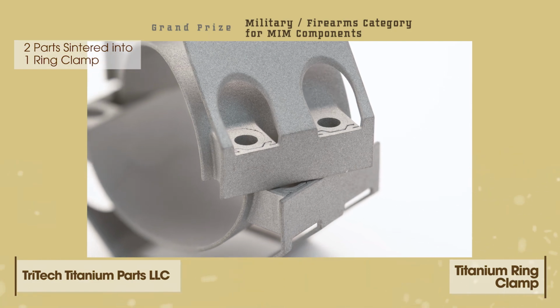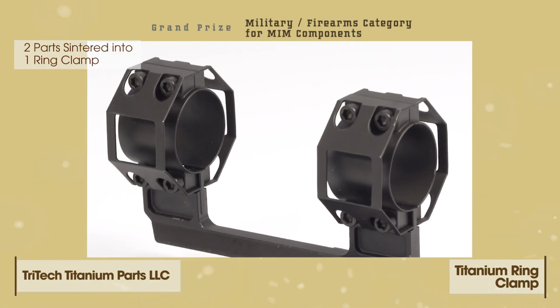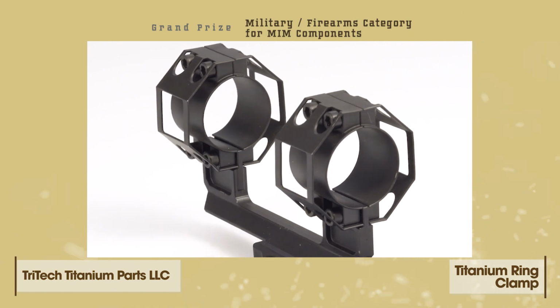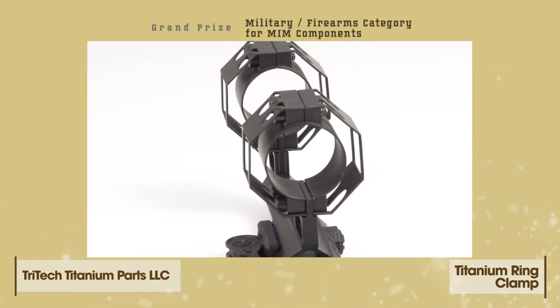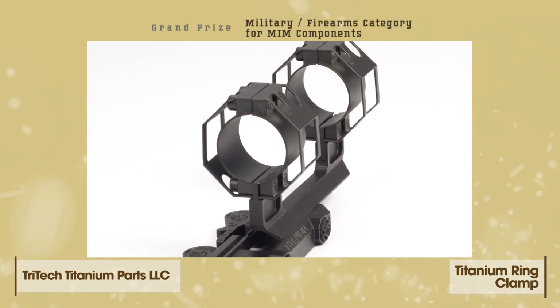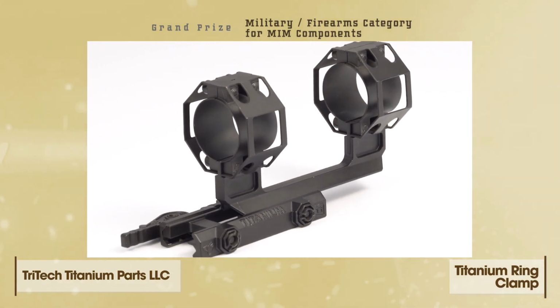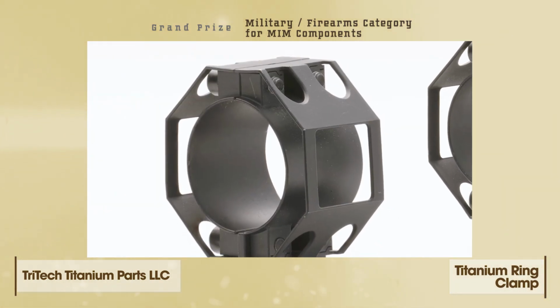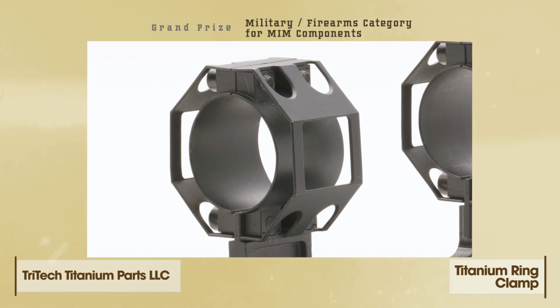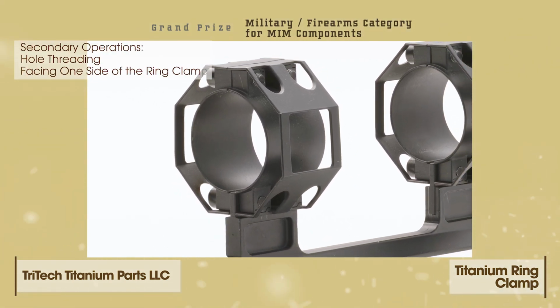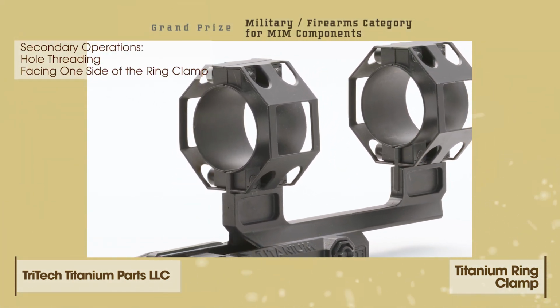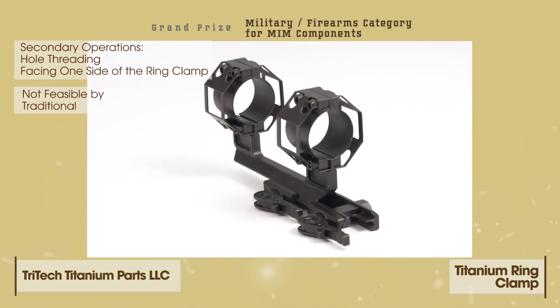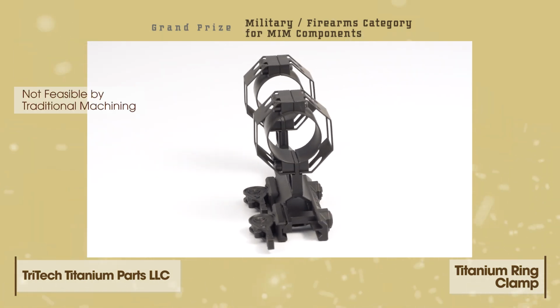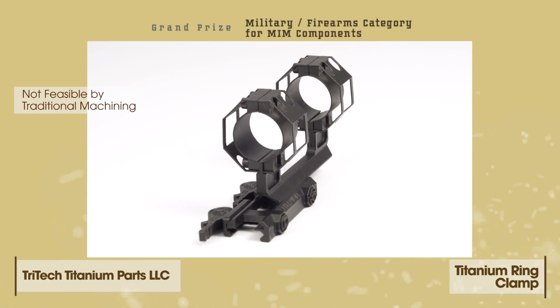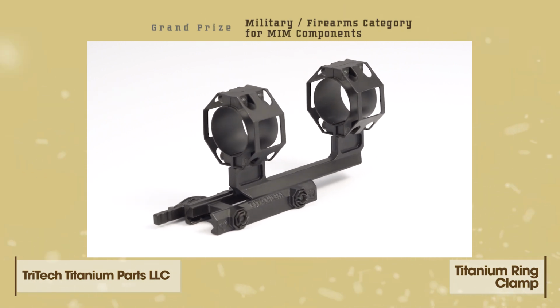Each ring clamp is made of 2 parts, an inner ring and an outer cage. The roundness of the inner ring is crucial to hold the magnifying scope uniformly and not mar the housing. The parts are molded separately, assembled in the green state, and then sintered to create one ring clamp. Although there is an interface present, the 2 parts sinter bond together, providing robust strength through the face machining of one side of the clamp and threading of holes during secondary operations. The entire finished assembly receives a flat black, thin film protective ceramic coating by the customer.